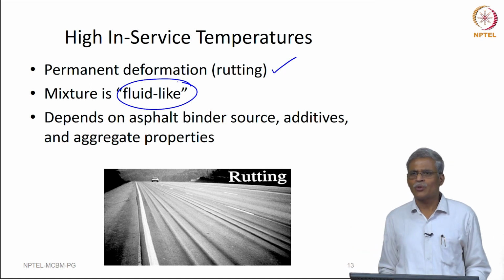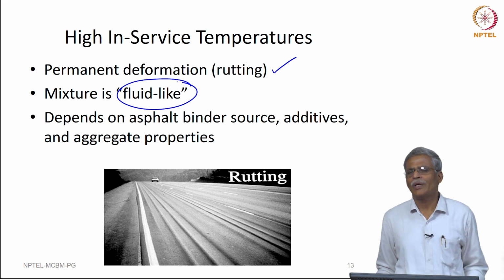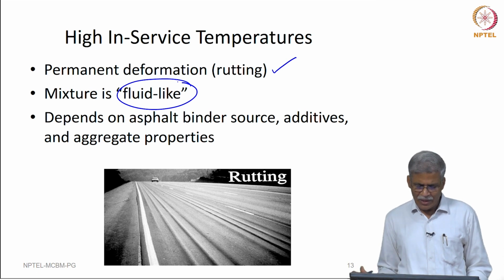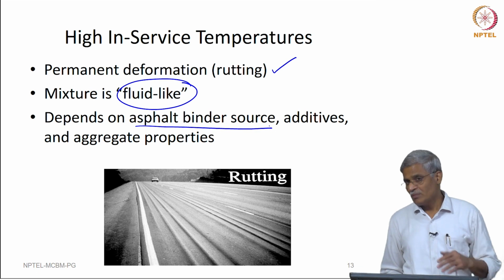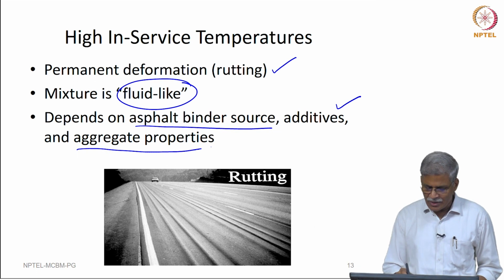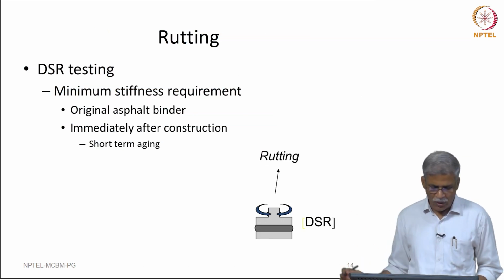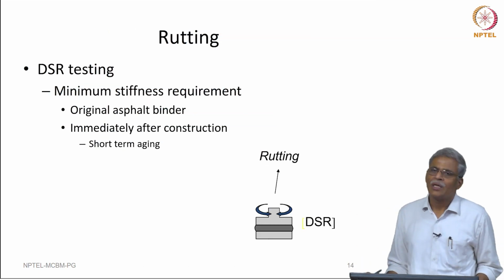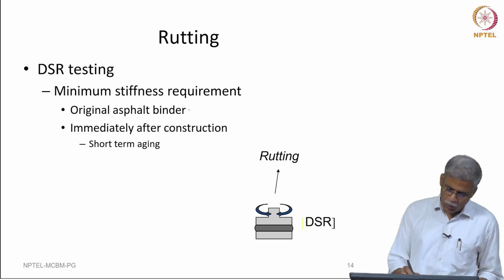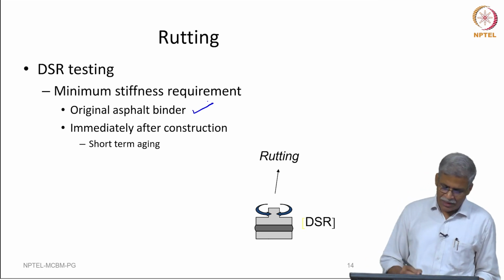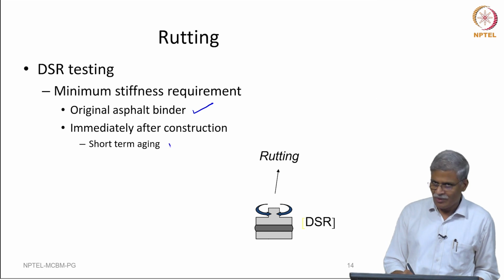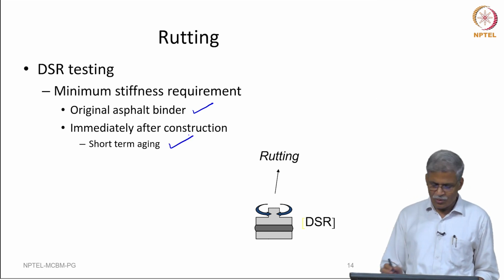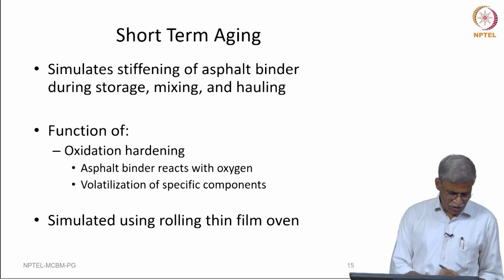in the lectures on linear viscoelasticity, we have clearly defined what is a fluid-like as well as a solid-like behavior. Such behavior depends on the type of binder, rather the binder source, whether we used any additives, as well as the aggregate properties, okay. So, how do we do this test? We will be doing this test under two conditions, in the original condition and after the short-term aging conditions.